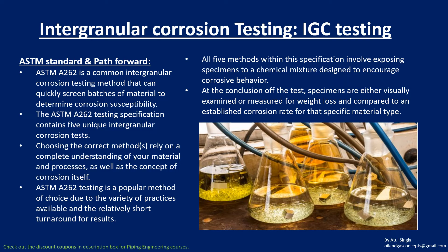These tests are popular because of their relatively short turnaround time. A specimen is inserted into one of the five specified acid solutions and kept there for a specified time duration. After removal, results are evaluated by measuring weight loss, or sometimes identified visually. This is the general methodology defined in ASTM A262.